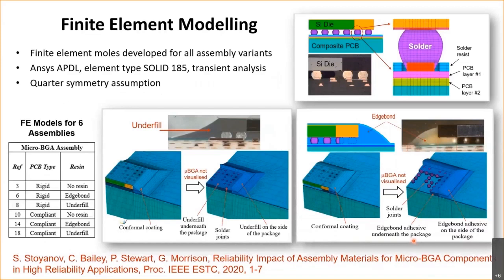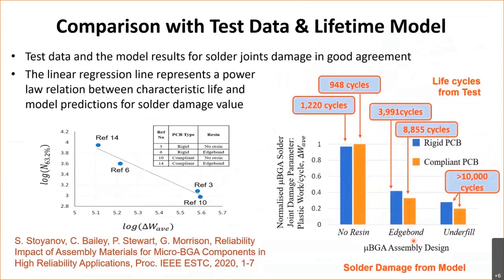Detailed finite element models were developed here, including the underfills or the edge bond with the conformal coating. We got very good comparisons here between the test data that I just showed and the simulations. Again, without using a resin, here we've got the compliant board and the rigid board, but without using a resin, not much benefit. We didn't expect that, but that was the case. It was also seen in the tests. But when using the edge bond or the underfill, there are significant benefits for these components. Here again, bringing together test data with simulation data, you can start generating these physics of failure models, models that relate cycles to failure to damage.